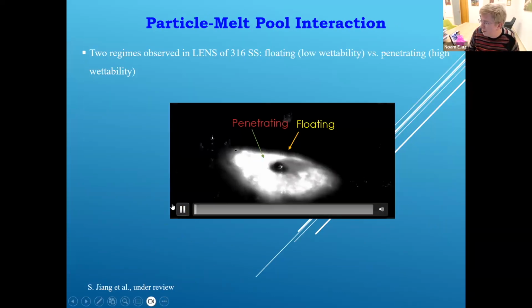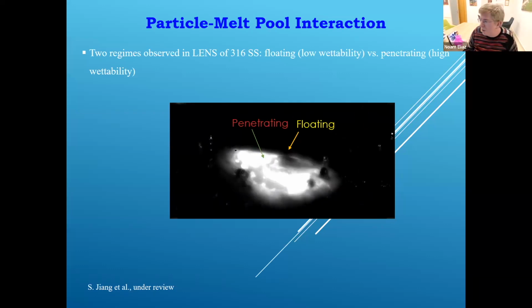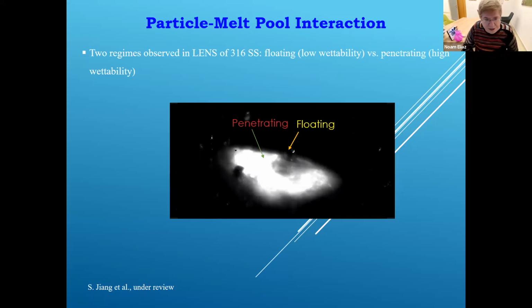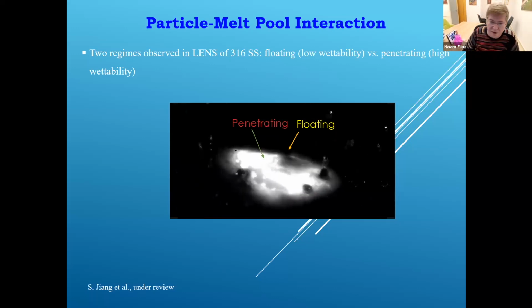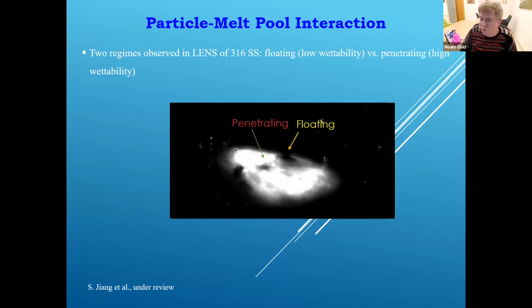So here you can see the interaction between the particles that hit the melt pool using the fast camera at the University of California, Irvine, with my colleagues, Professor Enrique Lavernia and Professor Julie Schoenung and their group. They moved to Austin, Texas recently. It is well established that two particle capture regimes are identified when the particle reaches the molten pool surface. One is the submergence regime, where you see the penetrating particle, and the other one is the floating regime. When the molten pool liquid can wet the surface of the particle, and the particle has a relatively high initial velocity, the particle will penetrate easily into the molten pool, resulting in the submergence regime. By contrast, if the particle and the molten pool liquid exhibit poor wetting, the particle tends to oscillate on the surface of the molten pool because of the surface tension force, therefore leading to a floating regime.